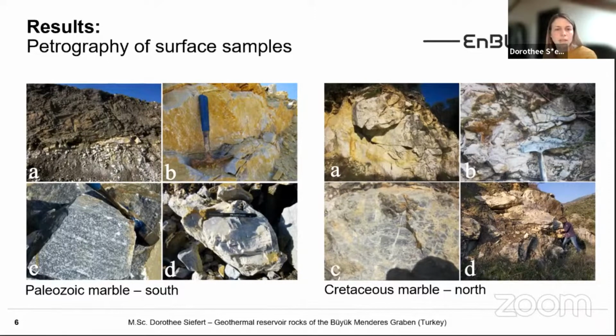And we did some EDX analysis of carbonate grains of this marble, or of both marbles, and this confirmed calcite as the dominant carbonate mineral. And the Cretaceous marble on the right is composed of a white marble. It's predominantly very fine-grained, massive, with also fine fissures, and both mainly composed of calcite.